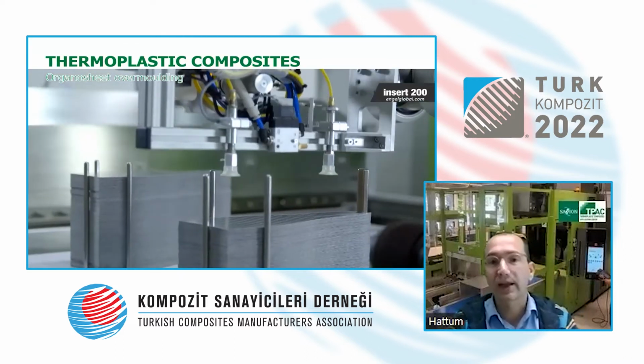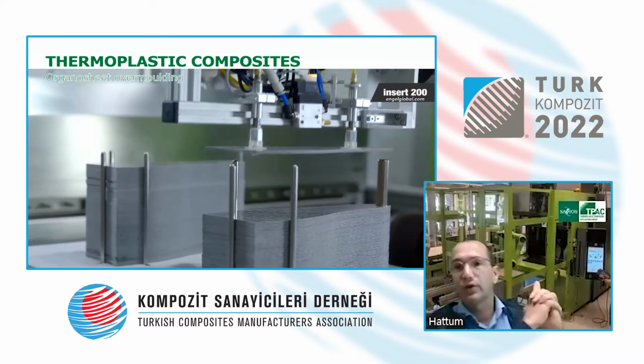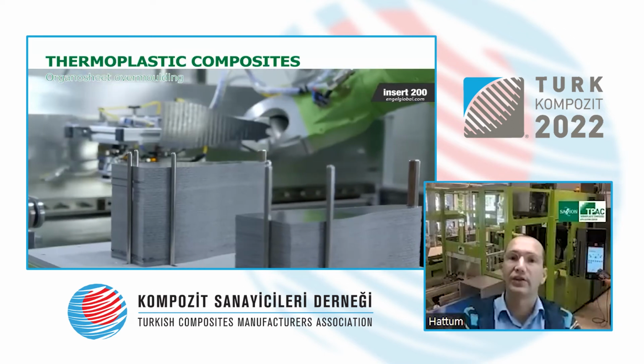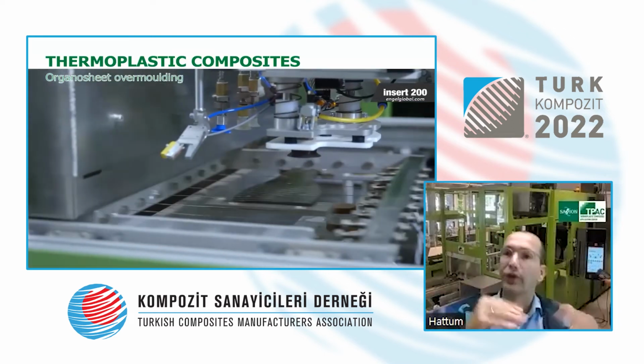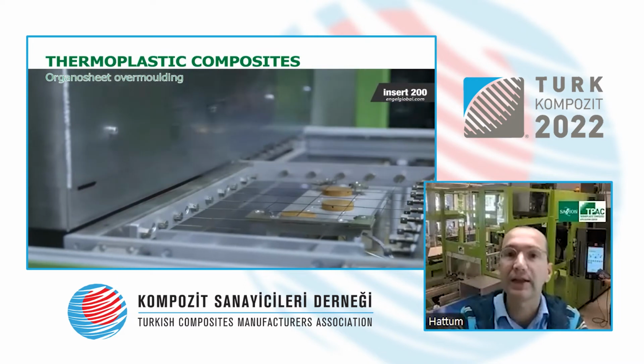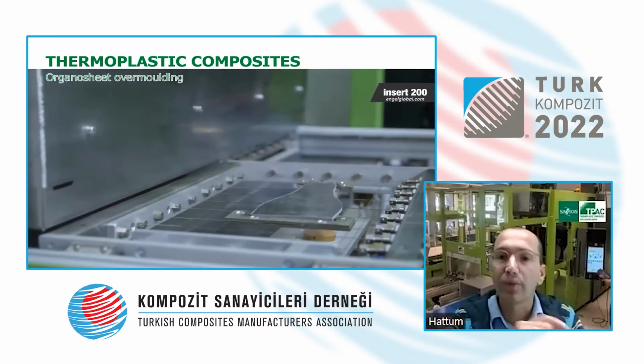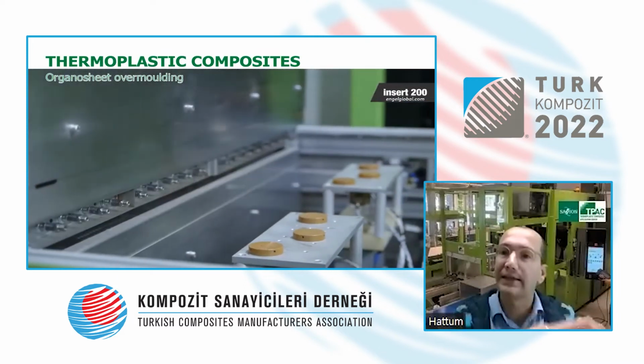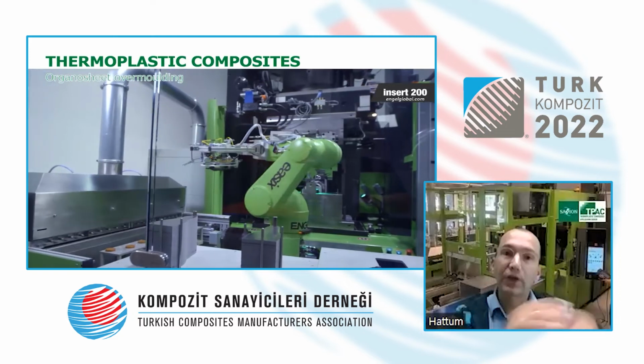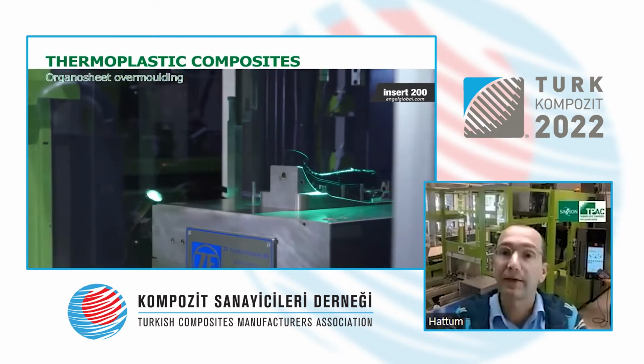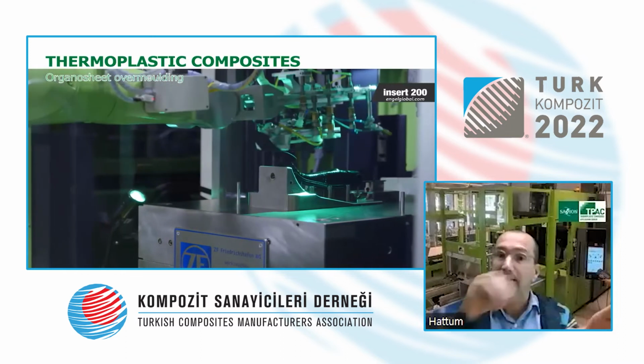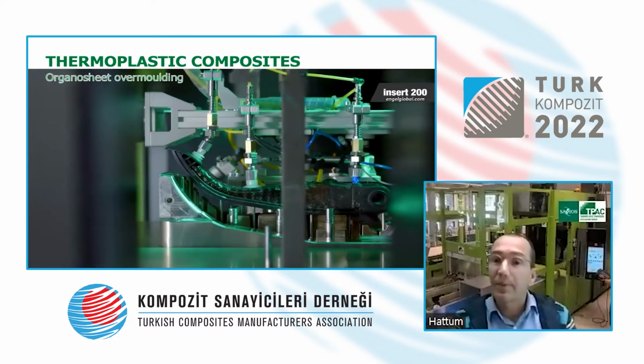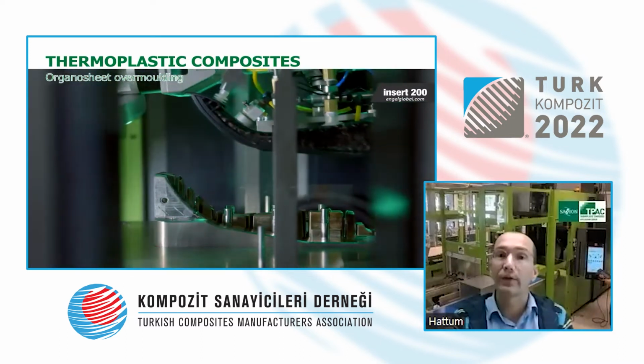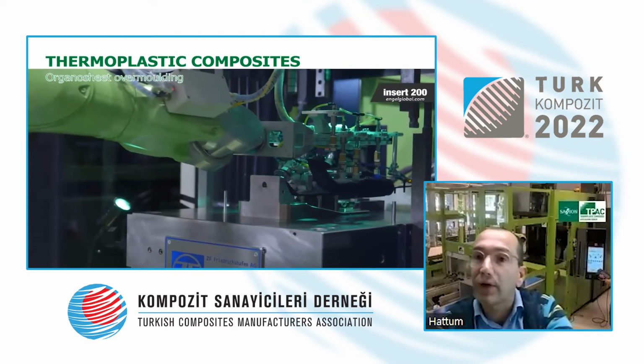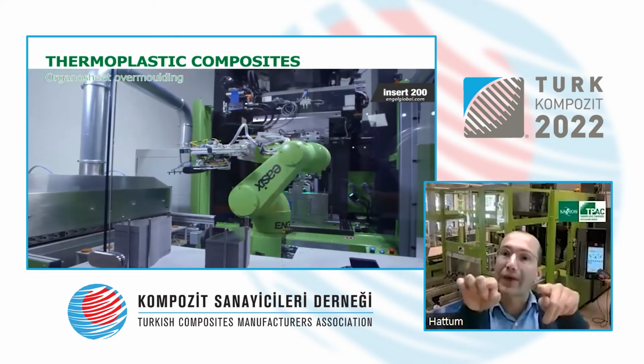And one of the central machines we use for that is what you can see behind it. In our case, it doubles as an injection molding as well as a compression molding machine. And I show a process of overmolding where a 0-90-degree pre-consolidated thermoplastic material goes in the oven. It's heated. Therefore, it becomes drapable. The previous part goes out of the mold fully automatically. You can see the molten prefab going into the machine.